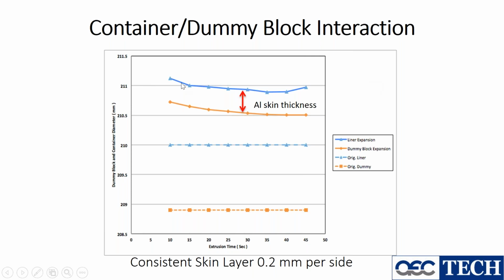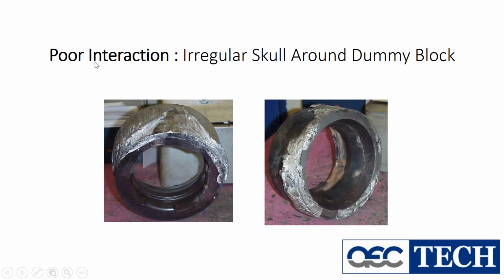So anyways, to back where I was, let me look through my cards. Oh yeah. So as the container either thermally and mechanically expands, we want to have a controlled amount of skin thickness that remains the same throughout the cycle. Okay, so what's very important is that if the skin thickness varies throughout the cycle, that means that we could introduce aluminum skin into the extrusion, which will show up as pickup on the extrusion. So if we have this poor interaction here between the ID of the container and the OD of the dummy block, we'll start to see blow by like this.